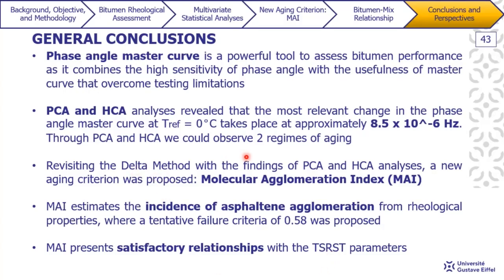And in this case, when we revisited the data using these findings, a new aging criterion could be proposed, which was the molecular agglomeration index, or MAI. MAI seems to estimate the incidence of asphaltene agglomeration from rheological properties. And based on other well-known failure criteria, we could propose a tentative failure criterion with a limiting value of 0.58 for MAI. And MAI seems to present a satisfactory relationship with the main TSRST parameters, such as failure temperature and